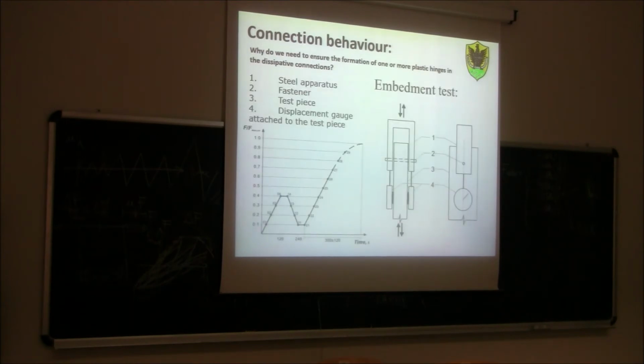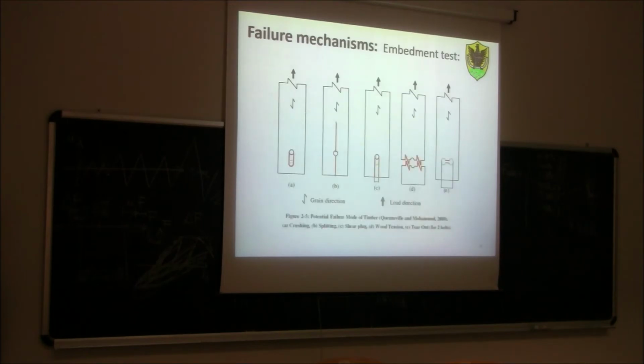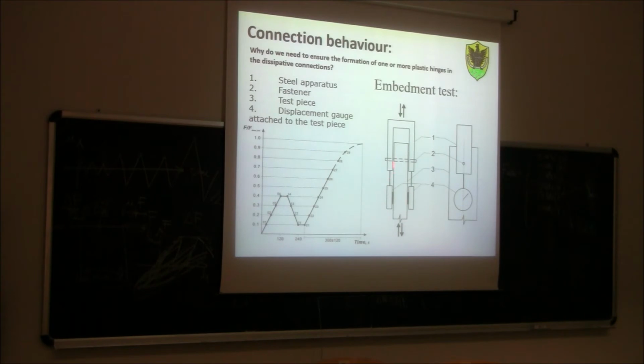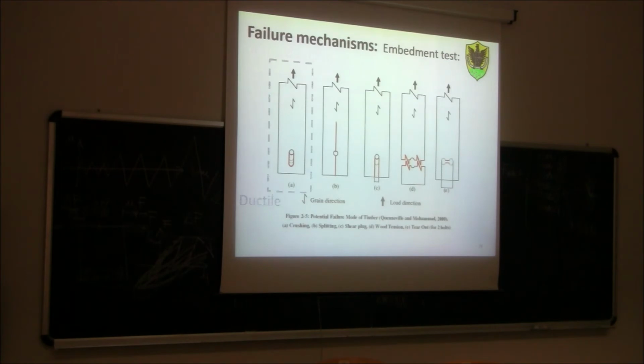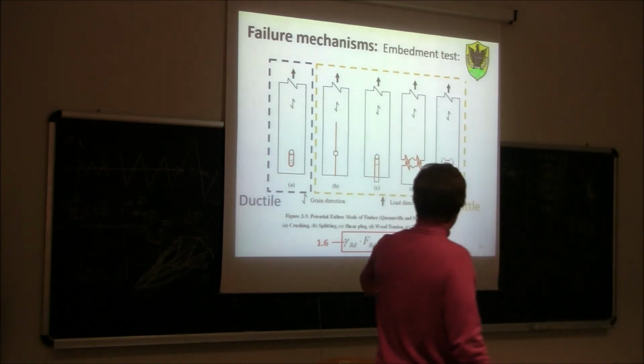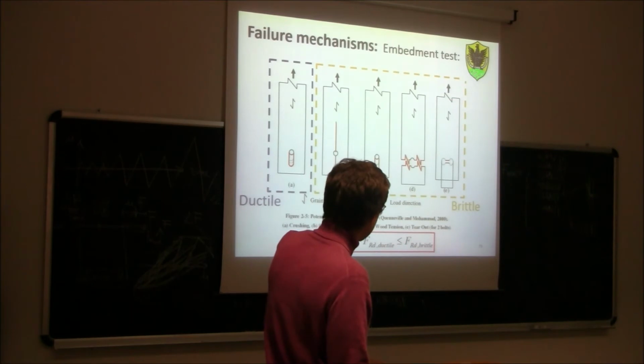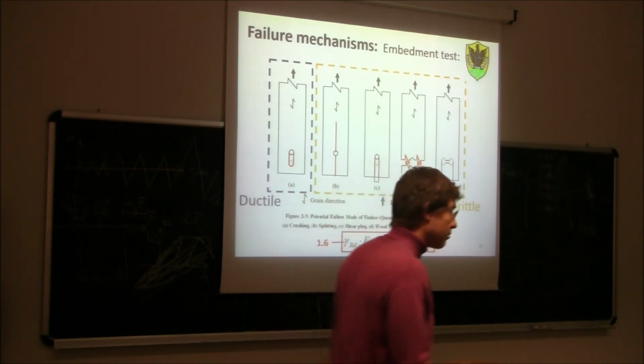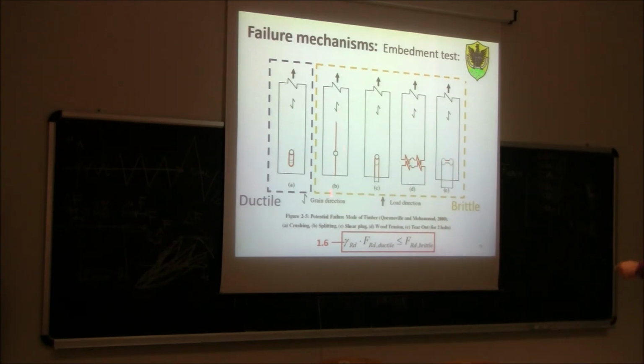So again, why do we want to have the formation of one or two plastic hinges in the fastener? First of all, if you remember, we said that when we do a test like this, so we pull a dowel in a timber member, we can get different failure mechanisms. The only ductile one is the one characterized by crushing, all the others are brittle. So all the brittle modes should be characterized by a strength which shall be greater than the strength of the ductile failure mode times the overstrain factor. In this case, since these failure modes here are very brittle, we have to use an overstrain factor of 1.6, no more 1.2. So 1.6 because splitting, tear out, shear plug and so on are very brittle.